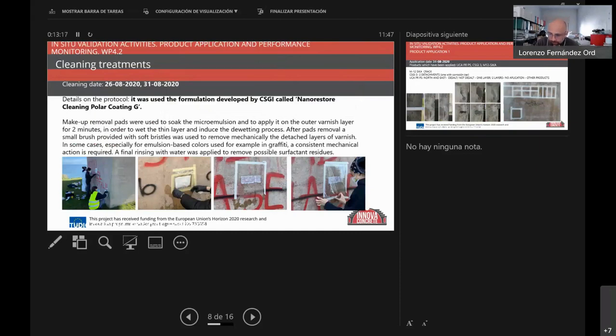Because we have this graffiti, we started cleaning the sculpture. As you see here, we have a lot of help from the University of Florence, which helped us with products in order to improve the cleaning. The graffiti, because we have this high porosity, goes into the little pores of the sculpture, and this product, called here Nano Restore Cleaning Polar Coating G, seemed very useful in order to take off the graffiti without damaging the surface of the sculpture.